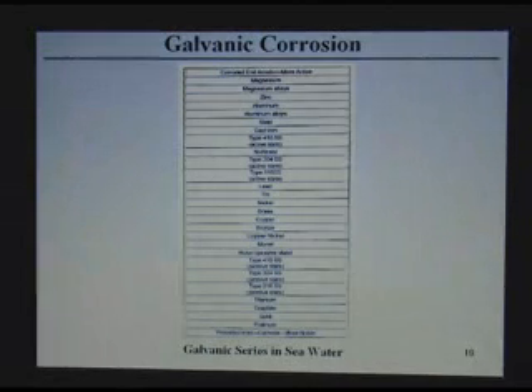This is the galvanic series, where the metals on the top are more active, they are anodic, and the more noble metals are at the bottom. For example, gold, platinum, graphite, they are more noble metals. Zinc, aluminum, magnesium, they are less noble. If you combine this with that, this one will corrode and sacrifice for this one. The steel is somewhere here, still not very resistant.